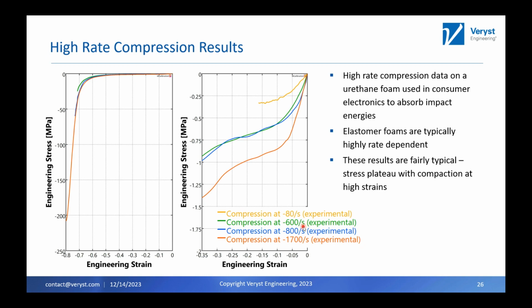I think this really shows one of the reasons why, particularly in foams, you really want to pay attention to rate. Foams have interesting behavior generally, right? If we start over here, they have kind of a linear or a pseudo-linear region, and then you get a stress plateau, which kind of looks like a yield behavior. And then as you follow that over here, at very large strains, you get what's called compaction. So this is basically when you've pushed all the air, if these are open cell foams, out of the material, and you're really starting to load whatever this foam is made of.